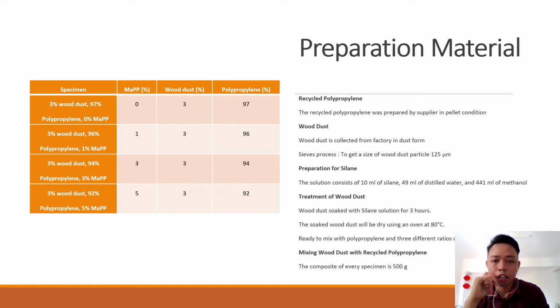Then for the preparation of silane, we need to make a solution for silane that consists of 10 ml of silane, 49 ml of distilled water, and 441 milliliters of methanol. This silane will be used to treat the wood dust. The wood dust will be soaked in the silane solution for 3 hours. After the 3 hours, it will be dried using an oven at 80 degrees Celsius. After it's dry, it's ready to mix with PP with a different ratio of MAPP.